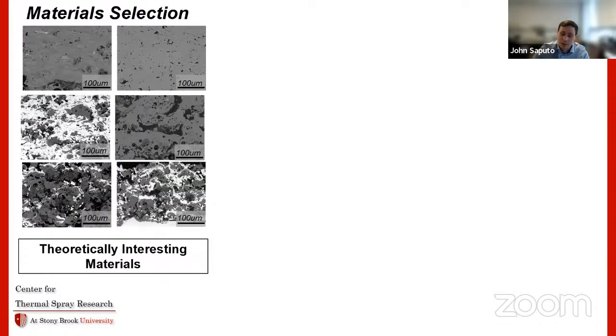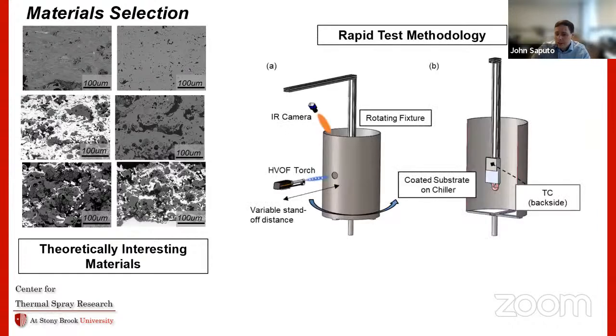So these specific materials are these 6 things here. They're all magnesium aluminosilicates. The 3 examples that I'm giving are mullite, which has been used in the aero industry, and steatite and cordierite, which are less commonly used. 3 of them are really brittle, low conductivity, low density ceramics. And then the other 3 of these things are actually composites that were developed using these brittle materials, sort of toughened with zirconia.